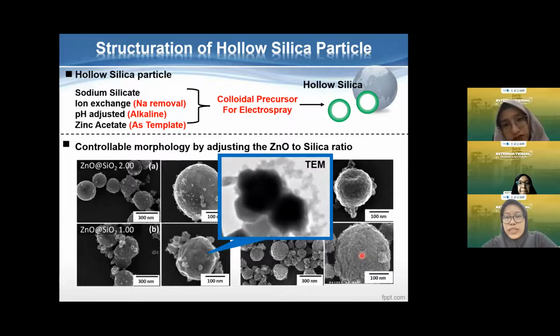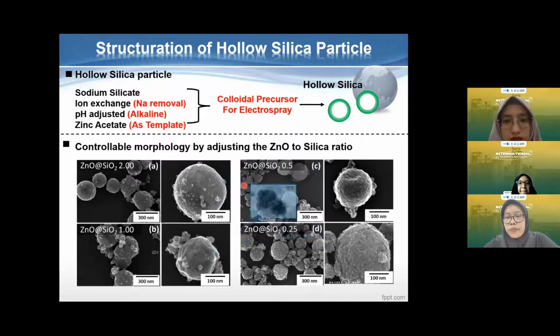If we use TEM, another characterization, to understand: the black part here is the zinc oxide particles, and the outside, more clear, is the silica particles, the small size here. So we cannot see the silica particles here because the amount of the silica particles is not enough to cover the surface of the zinc oxide particle.